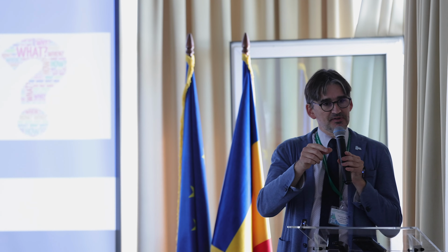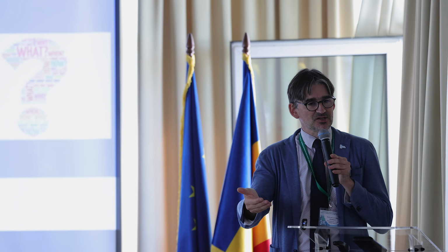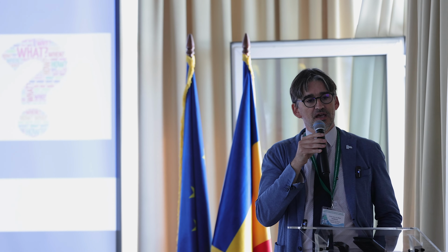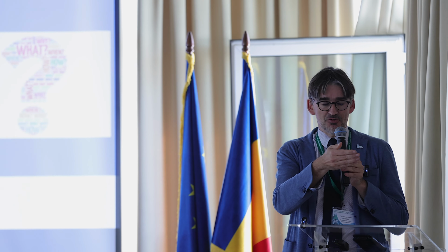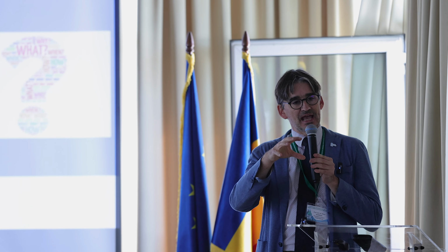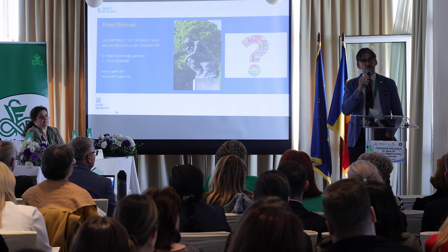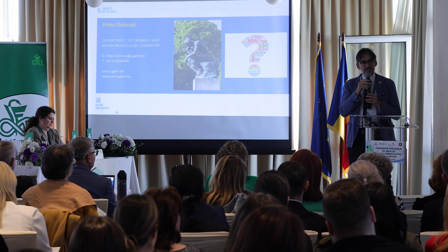Now comes the main limitation. If those polymers are water soluble, then from the moment that you spin them from different solvents, from the moment you bring them in contact again with the water environment, quite often they again go into solution. So the main limitation, in my humble view, is the fact that you have to be able to cross-link those fibers after electrospinning. And cross-linking in the solid state is not always the easiest aspect. And as you mentioned yourself, quite often polymer blends is the way to go. So then we make a combination of gelatin, collagen, alginate with some synthetic polymers. And those synthetic polymers then trap also the biopolymer in the fiber mat. So I think that new chemistries to enable an efficient cross-linking after electrospinning will certainly be an important aspect to be looked at.